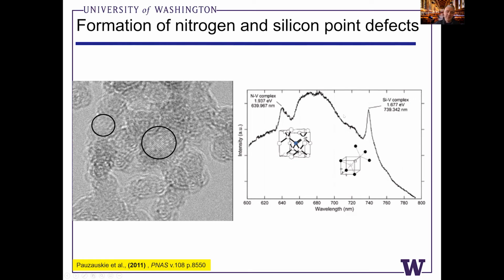But surprisingly, way back in 2011, when we first looked at the PL of these materials, we saw really pronounced emission at about 638 nanometers and about 740 nanometers. I had never worked with diamond before and was scratching my head, wondering what is this emission coming from? We were just trying to get Raman and had all of this photoluminescence messing up our Raman signal. And looking into the literature, these peaks index very nicely to the negatively charged NV center and the negatively charged silicon split vacancy center. So we had been making these point defects accidentally.